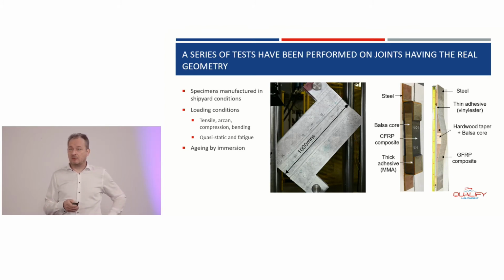at the center, I'll come back to that, is what we call an Arcan type of test, where we do loading, which is under an angle to the specimen, to have multi-axial loading in the specimen. These specimens are now too large to be put into an environmental chamber for salt spray aging. So we had to develop an aging protocol that was able to mimic the same conditions.